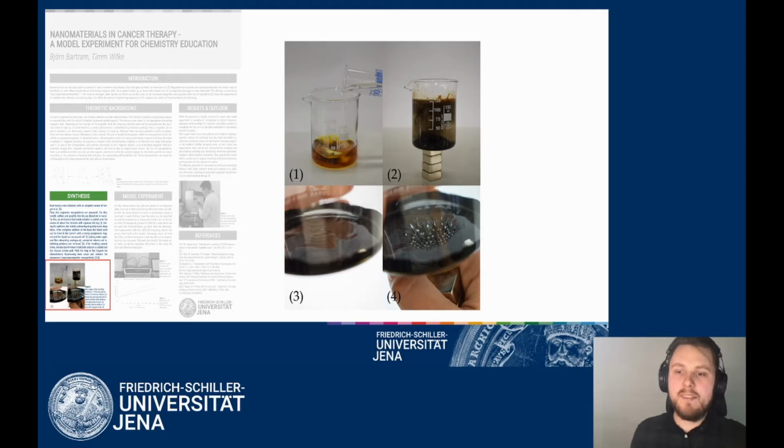To stabilize this, I call it mud at this point, we use tetrabutylammonium hydroxide, an organic base, which can sterically and electrostatically stabilize the nanoparticles so they won't get stuck with each other, so you can get a ferrofluid.